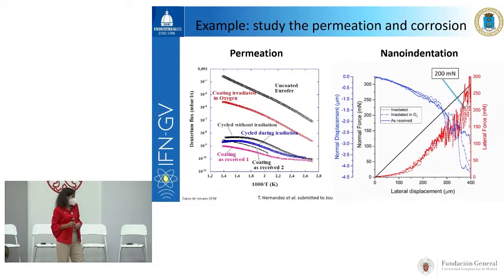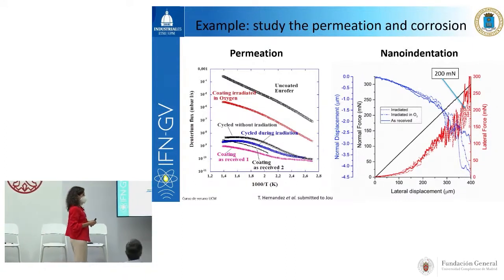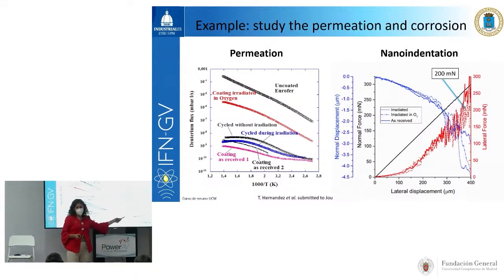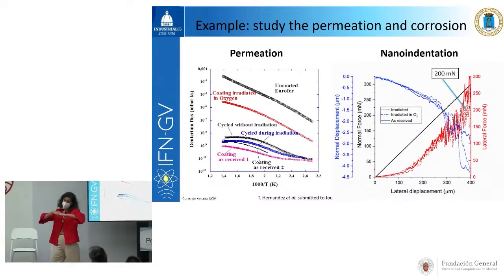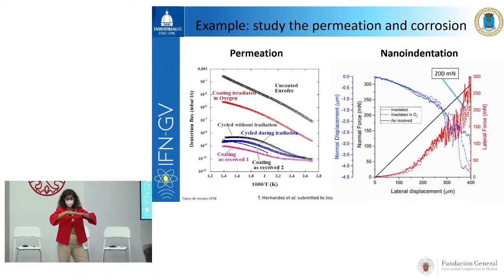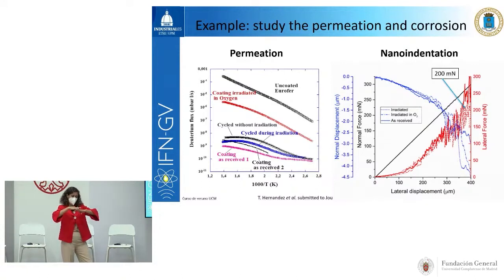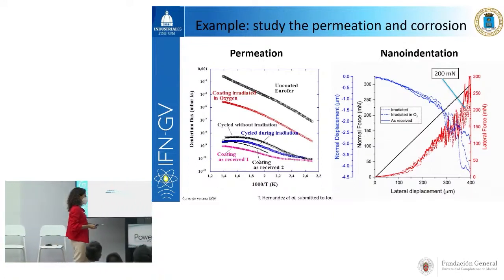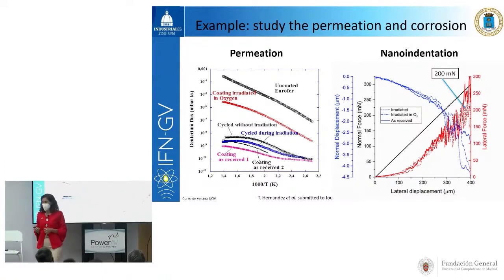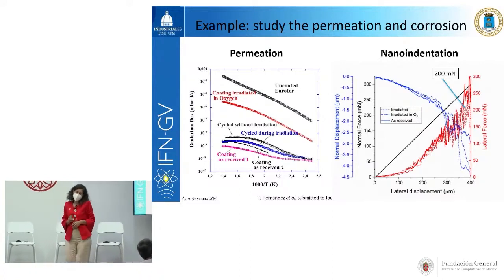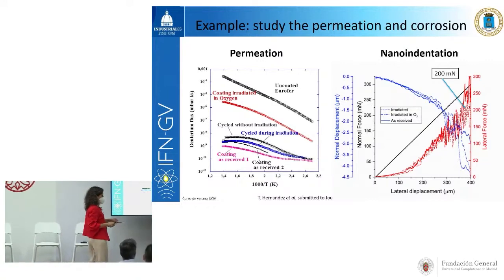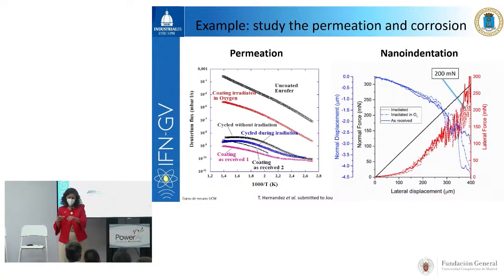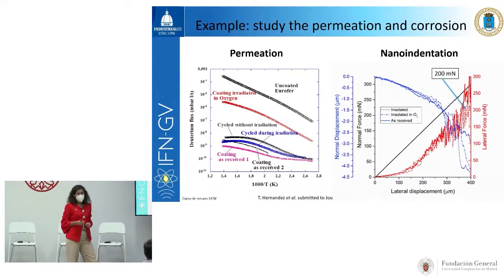There is also another very important thing to be considered when dealing with this kind of coatings deposited on the Eurofer, and it is the adhesion of the coatings to the surface. We are depositing one material on the other. We are creating defects that can create stress in the material, and then the material can delaminate just because of that stress. So here we have shown the adhesion of the coating to the substrate, and we see that basically there is no delamination. This was measured by the nanoscratch technique, which I'm not going to explain, but basically we observed that the adhesion is the same before and after irradiation.